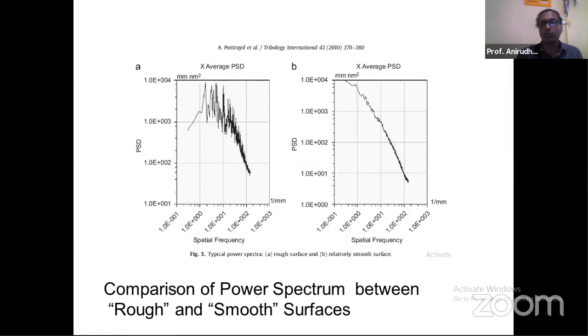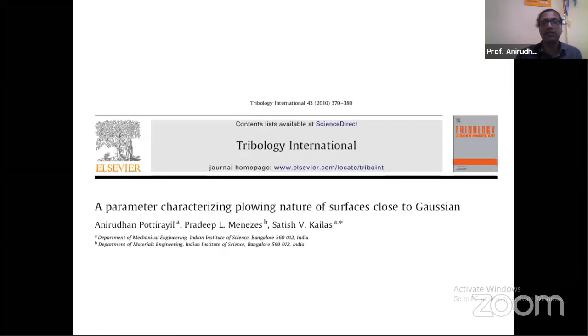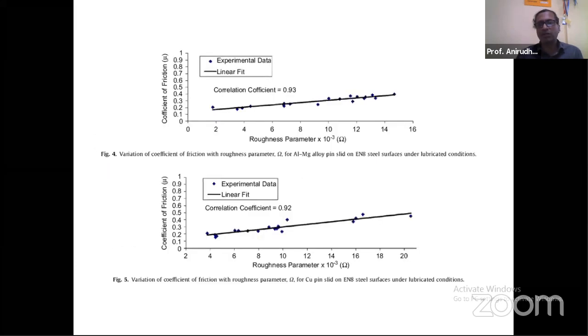So we use those two parameters, RQ and the mean frequency, and these results are published in this paper, a parameter characterizing ploughing nature of surfaces close to Gaussian, which was authored by me, my senior Professor Pradeep Lansi Meneses, whom I mentioned, and our Professor Satish Kajlas. And when we plotted this hybrid parameter, which is a combination of our RQ value and this frequency parameter, you can see that it becomes dimensionless. So we plot our coefficient of friction value against this newly formulated roughness parameter.